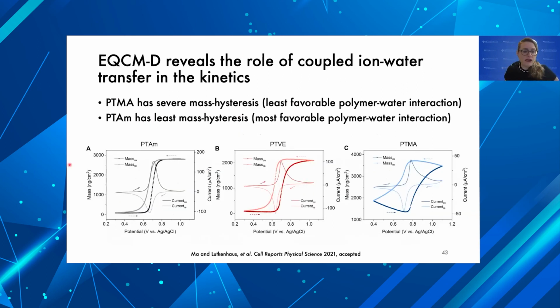When we do EQCM-D and we can measure the mass change during the cyclic voltammogram, as we did in the last study, we can see that these water-polymer interactions manifest as hysteresis in the mass transfer. If you look at this plot with the square boxes, that's the mass change as we oxidize and reduce the polymer. The mass increases because we're doping the polymer and the anion is coming in. PTAM has the least mass hysteresis, and then PTMA has the most mass hysteresis. So this is showing how the sluggish electron transfer kinetics manifest as well in sluggish mass transport kinetics for the polymer.